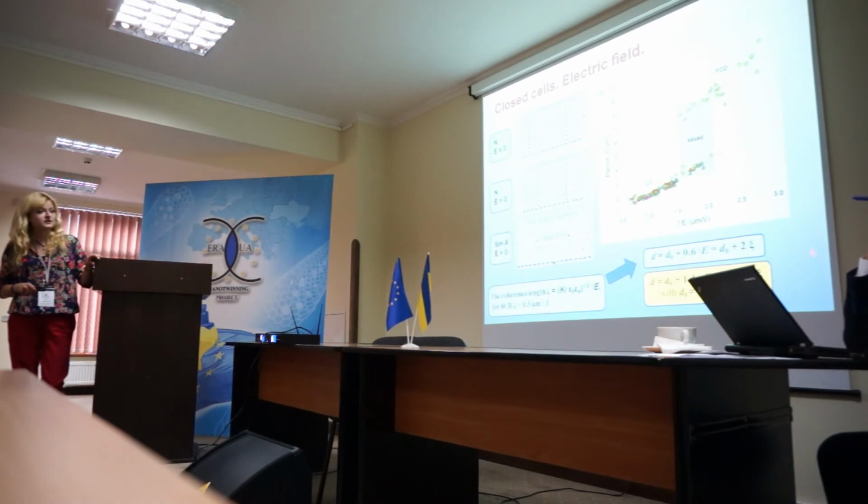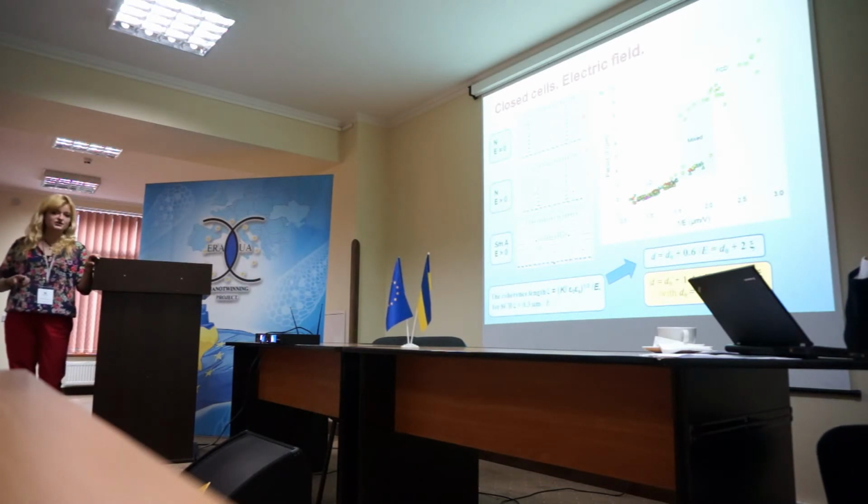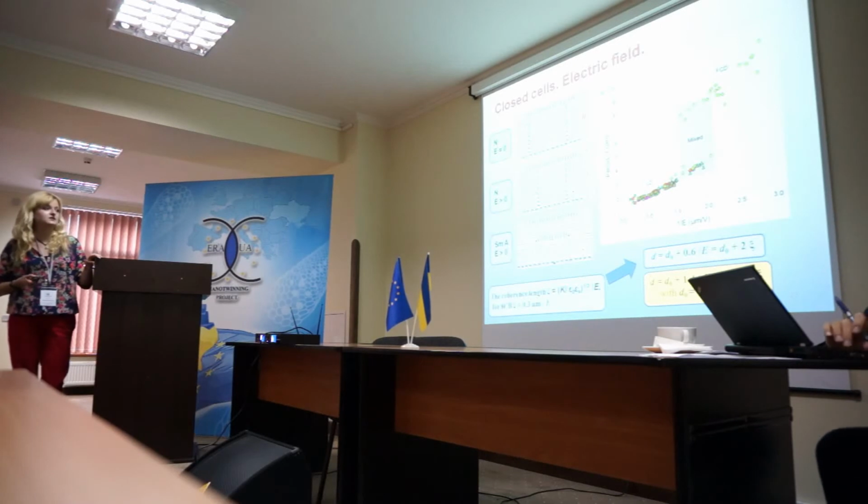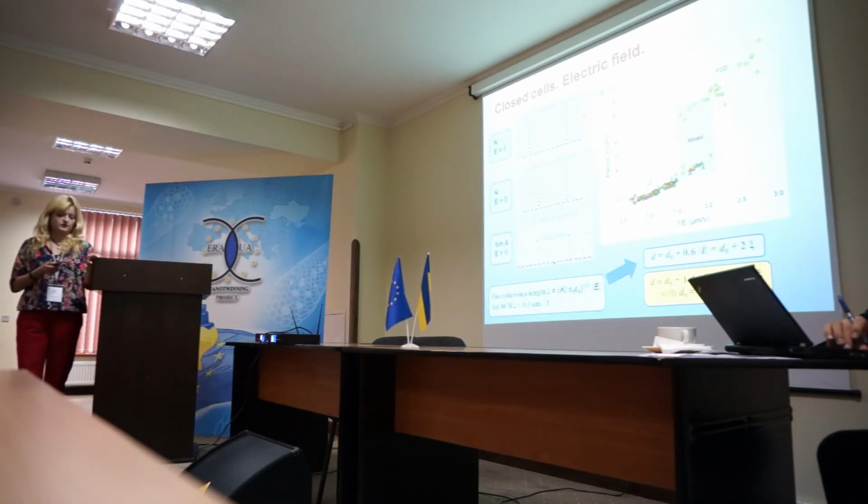But as you can see, for the zero field we had a slope of 2, and now we have a slope of almost 5. That suggests that the electric coherence length must be larger. Let's say it is the effective thickness of our sample, and it seems that it must be larger than we expected.